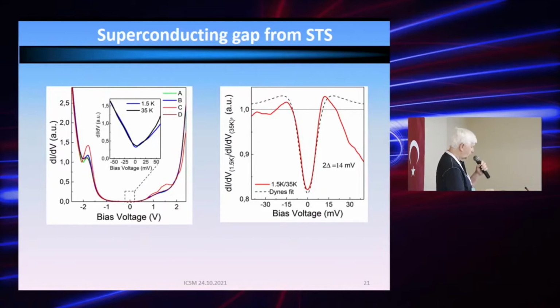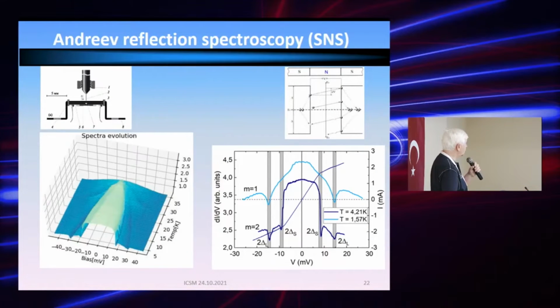After hard work, we can reveal a tiny signature of the superconducting gap, which may be seen as a 20% drop in the vicinity of the zero bias voltage. But nevertheless, the energy scale is consistent with what is found from ARPES. Remember, I showed 8 milli-electron volts, the large gap. So this instrument is not very helpful for us.